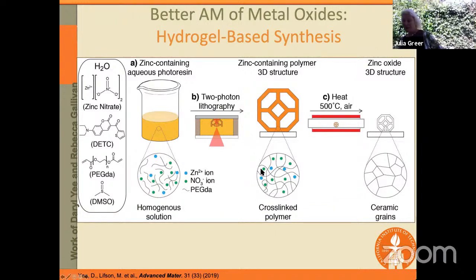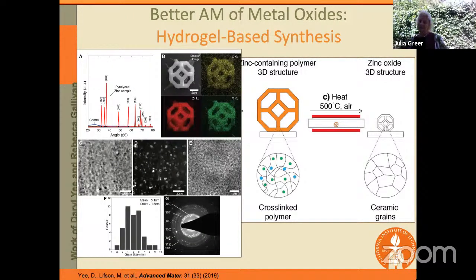And then now that you've swollen in these metal ions, what we can do is subject it to heat, and through a process of calcination, we can get rid of the organics again. And what we end up with is a zinc oxide. So this time it's a functional oxide unit cell that's made entirely using water, effectively. Yet again, it's a very nanocrystalline architecture.